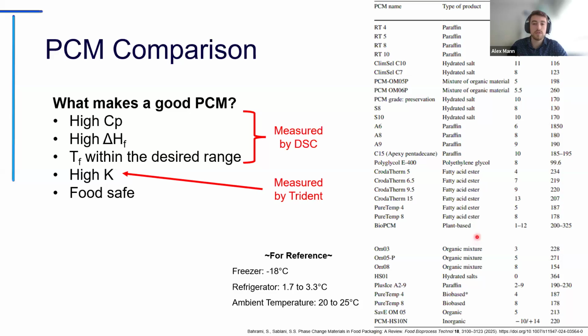So if I was going to use a PCM, what would I look for? For this example, I like using the lunchbox example. If I want to keep my lunch cool, let's see what I'd use. We see some of them melt at 10, 11, or even some of them melt over a large range because they're not a homogeneous sample. There are many things melting together. That might be a little bit too high for my liking. I might want to pick one that melts around 4, or maybe 3 or 0.